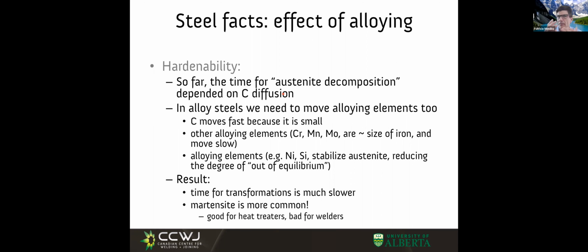Indeed, I mentioned to you when we were talking about consumables, how manganese and silicon pick up oxygen from rust. But if I'm using a high manganese wire in a clean plate, the manganese is gonna stay inside the metal and can give us trouble, because alloying elements also change these start and finish times in our phase transformations.